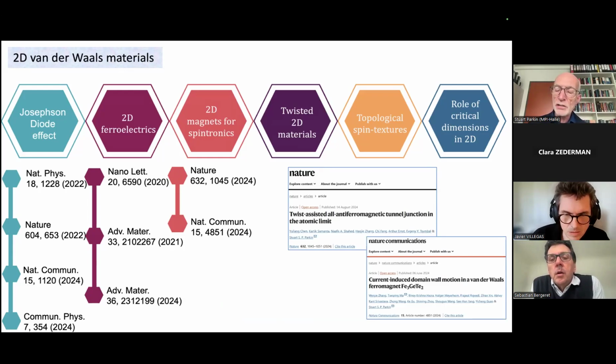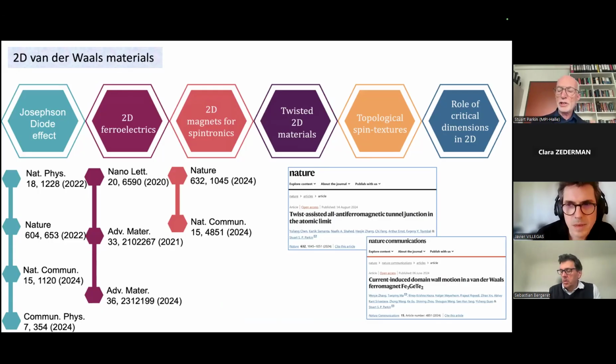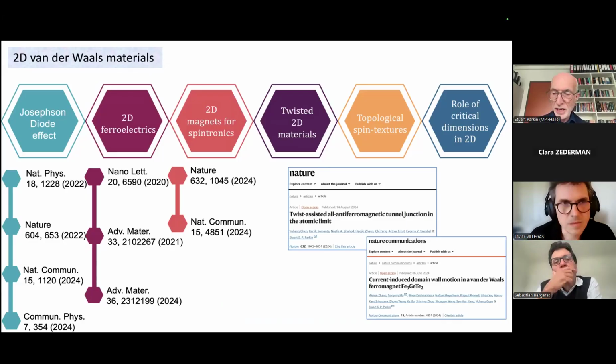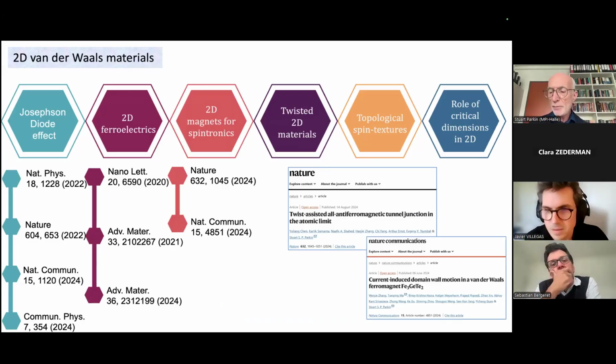This is the Fe3GeTe2. And it turns out that the domain walls are extremely mobile as compared to conventional materials. And we can actually move with current pulses domain walls at very low temperatures, even down to the lowest temperatures, which isn't possible in some of these conventional materials because of pinning of the domain walls.